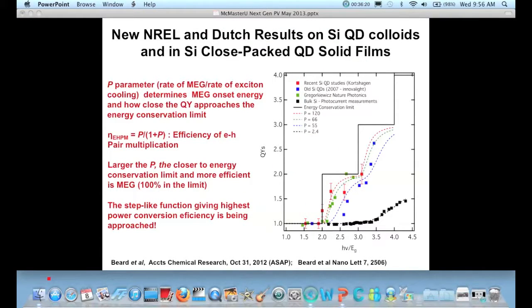And more recently, these new results show that we're, as I say, beginning to approach the threshold of 2. So just in the past few months, we have some new data with isolated silicon colloidal dispersions of quantum dots showing that there is a step change in the quantum yield just when you hit 2. So if the photon energy is 1.98 times the gap, you just get a quantum yield of 1. If it's 2.02 times the gap, it jumps up. Now, ideally, you'd want it to follow this staircase function, but the red squares are what we actually found. So it's beginning to show some of this staircase-like characteristics, but it's still not yet equal to a step function.